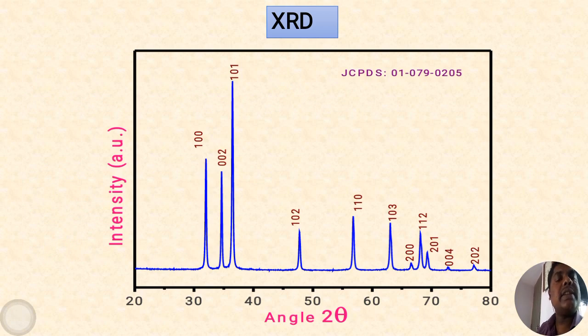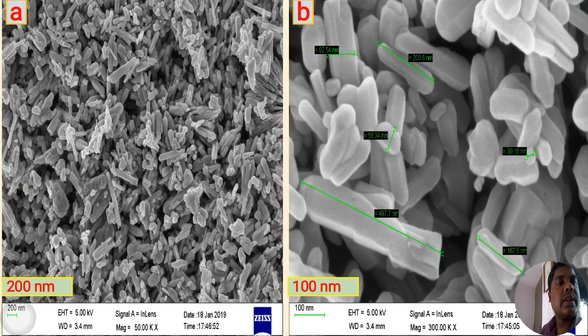Now, check this XRD analysis of my nanostructure. I matched this nanostructure with JCPDS card number 01-079-0205, and we get an amazing result, intensity along the 101 axis. That is a very high intensity. Therefore, here is a clear-cut indication of formation of nanorods with hexagonal wurtzite structure, that is the geometry of our zinc oxide and cobalt doped zinc oxide nanorods.